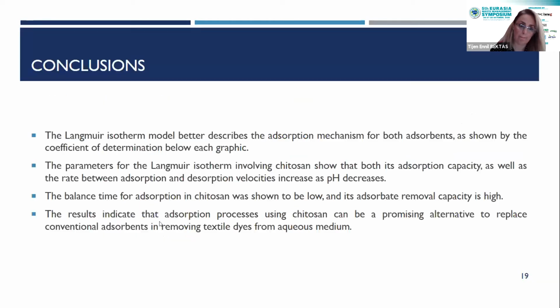Our conclusions with this paper are: the Langmuir isotherm model better describes the adsorption mechanism for both adsorbents, as shown by the coefficients of determination below each graphic. The parameters for the Langmuir isotherm involving Chitosan show that both its adsorption capacity as well as the rate between adsorption and desorption velocities increase as pH decreases.